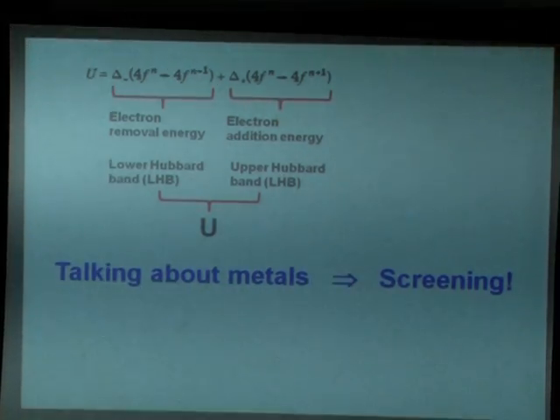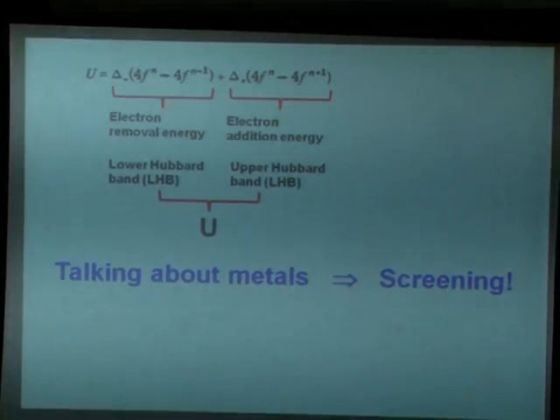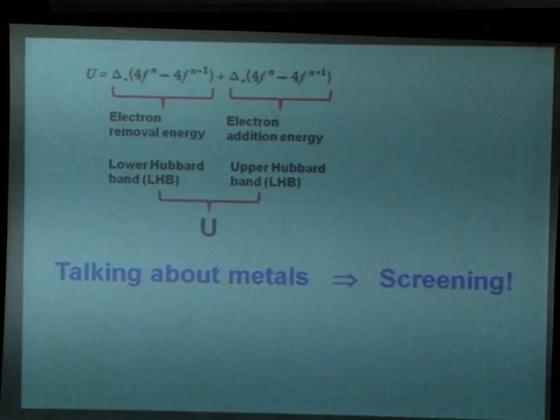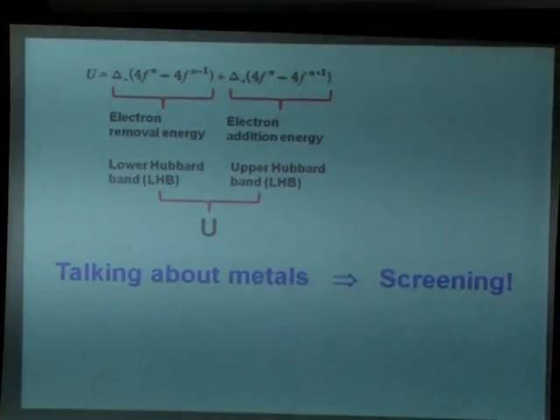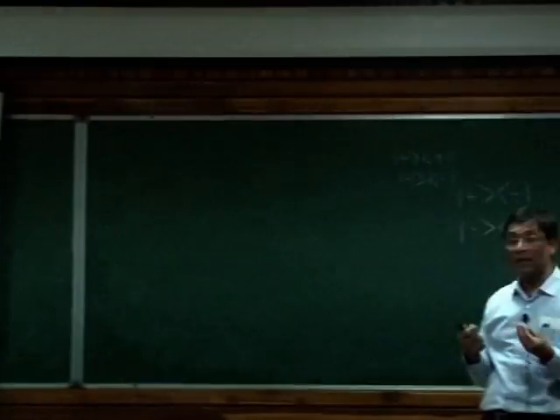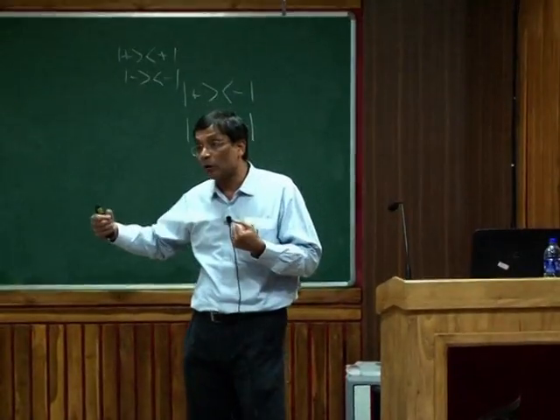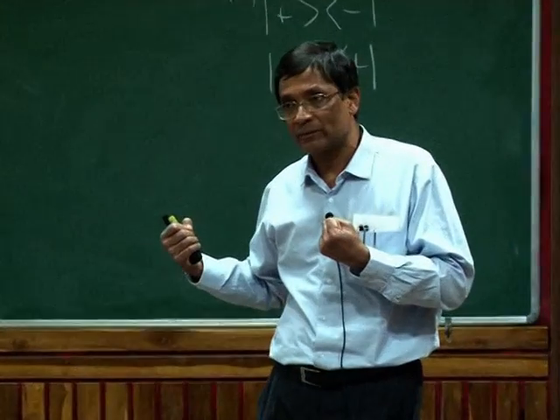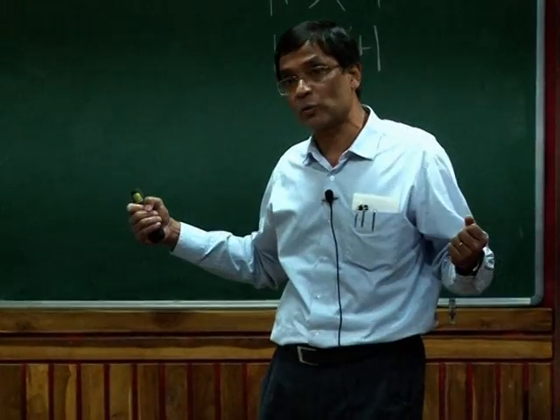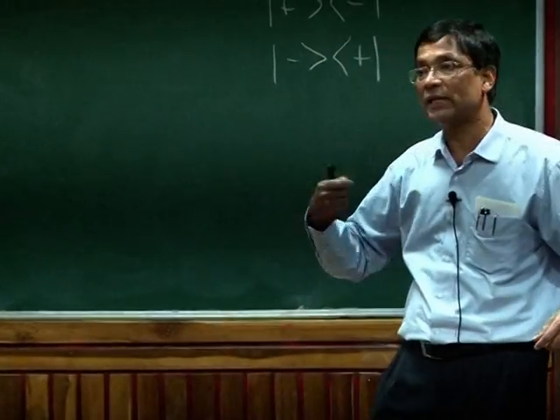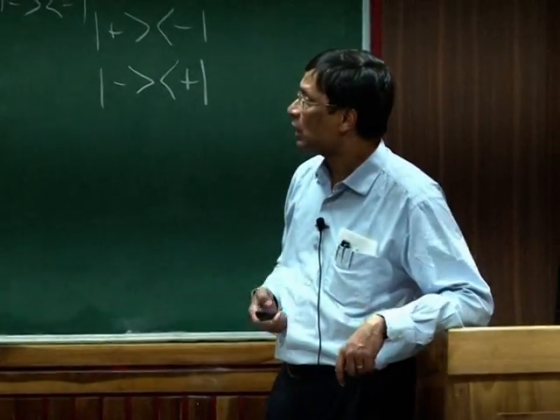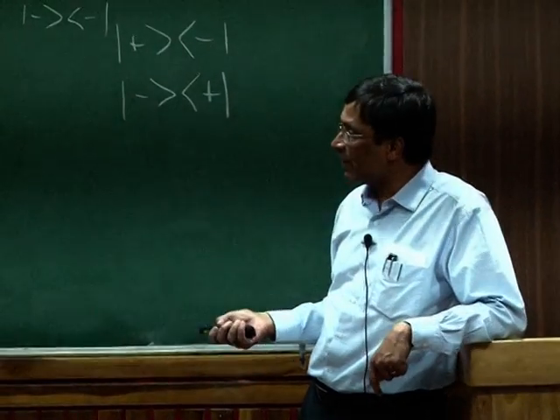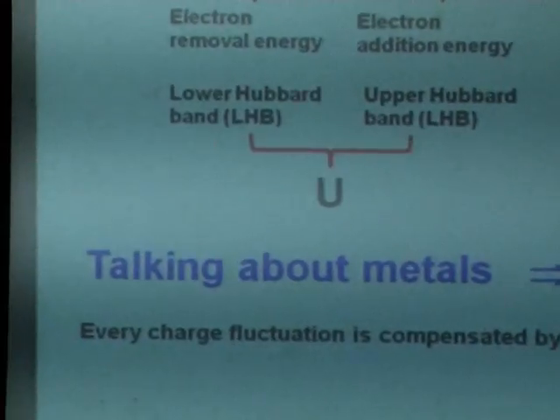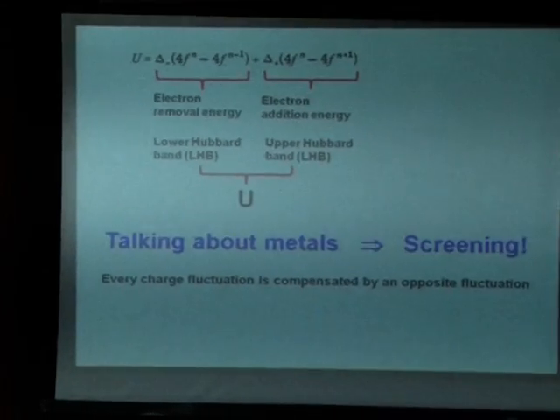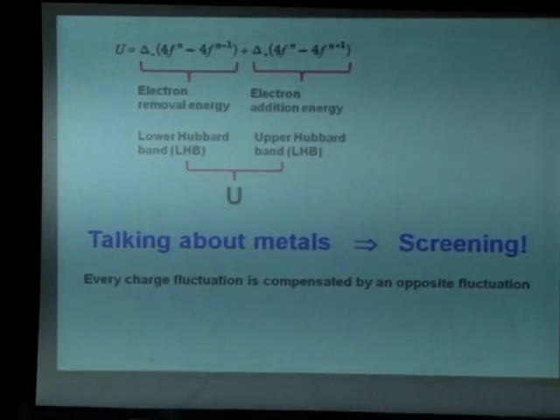But we are talking about metals and not atoms. So when I move one electron from one side to the other, all the other n electrons that I talked about, I pretended that they don't respond, but they respond hugely. Simply because a metal cannot allow a potential gradient inside itself. The free electron will respond to screen out that potential. And so the other electrons respond hugely, and how do they respond? So what they have said is that every charge fluctuation will be compensated by an opposite fluctuation in another orbital on the same site, which means a complete screening.